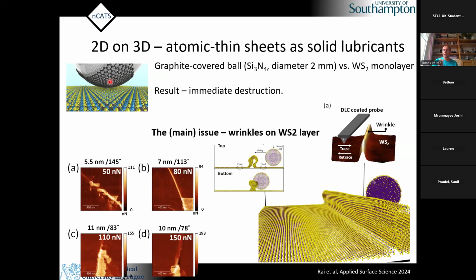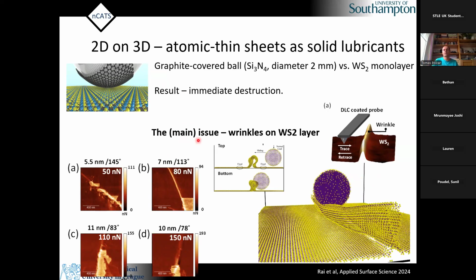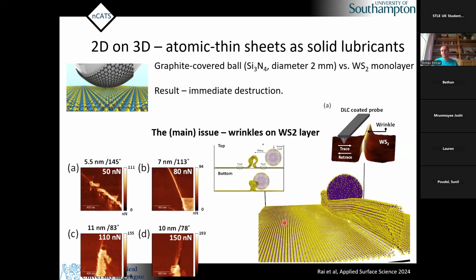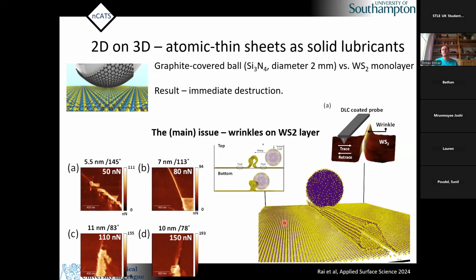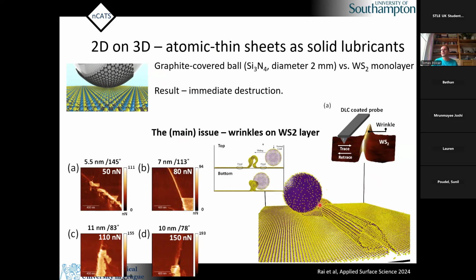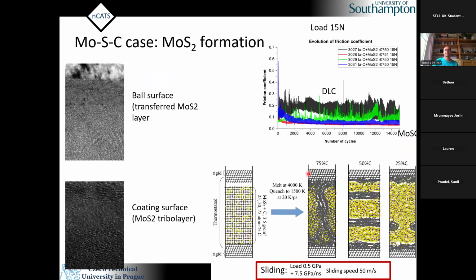So it didn't work, and yet we wrote a paper, and it was published in Applied Surface Science, where we explain why it doesn't work. We said, look, these wrinkles get broken very quickly, and we developed a kind of model. You see the ball, which is the tip, which is going. I don't know why the movie is not continuing forever, but you see that we have a model which shows how this kind of wrinkle breaks. And because we cannot avoid the wrinkle, we cannot really make this material work. So you see that even if you fail, you can get something.